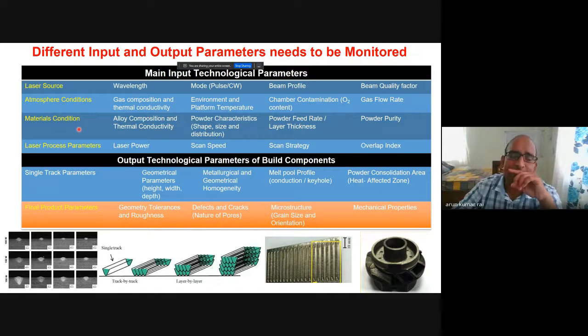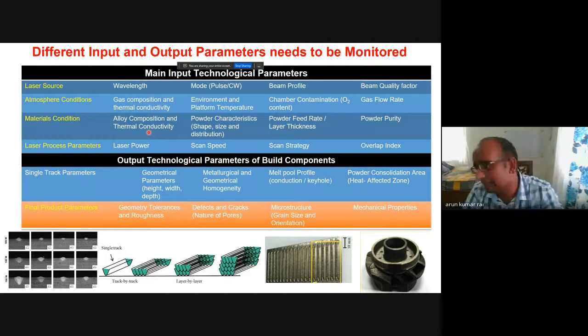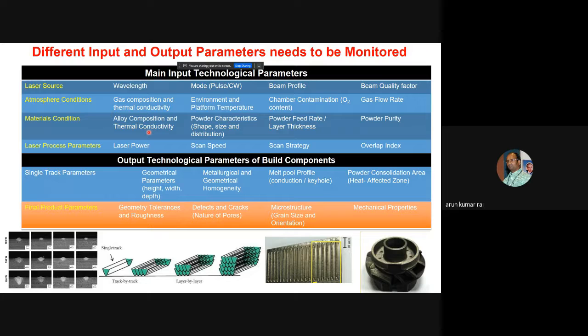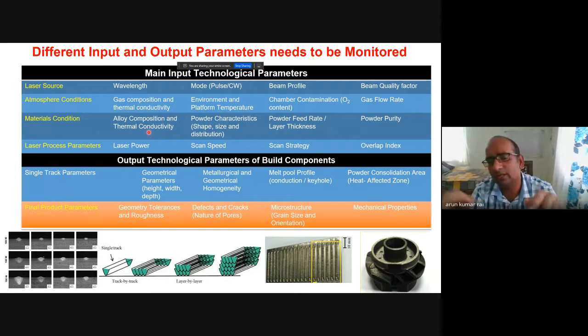Next comes the material condition. Material condition means whether you are using a pure material or some alloy. When you are using an alloy, sometimes some alloys are prone to form intermetallic phases, or they are not suitable. Suppose you are doing multi-material. In multi-material, one metal may not be wetting the other metal. That means wettability, or you can say a surface tension difference is there. Then again, the material will not be properly deposited. Once the melt pool forms, if it is not wetting your substrate, it will form globules over it, and those globules will lead to porosity formation. I will discuss more detail later.